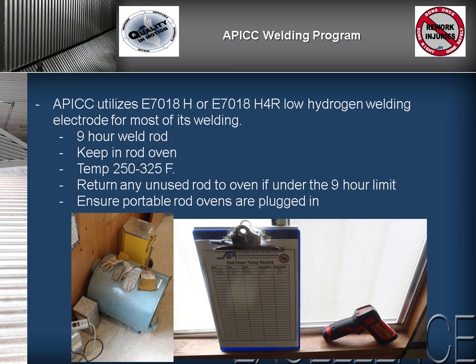Rod ovens for this electrode shall maintain a temperature between 250 and 325 degrees Fahrenheit. If portable rod ovens are used, ensure that they remain plugged in once you arrive at your workplace and during production.